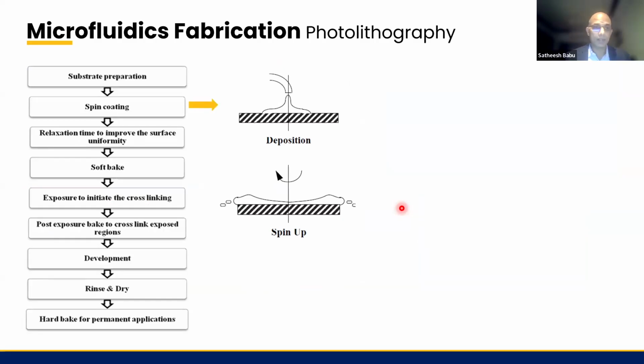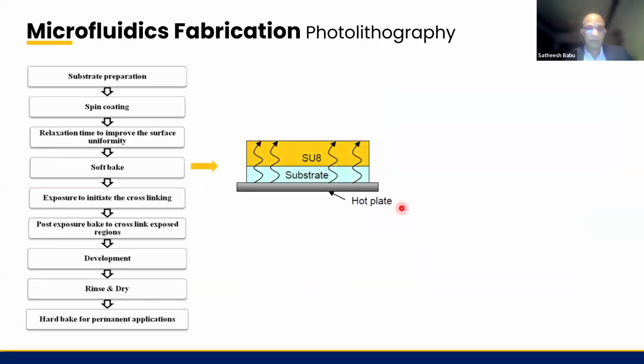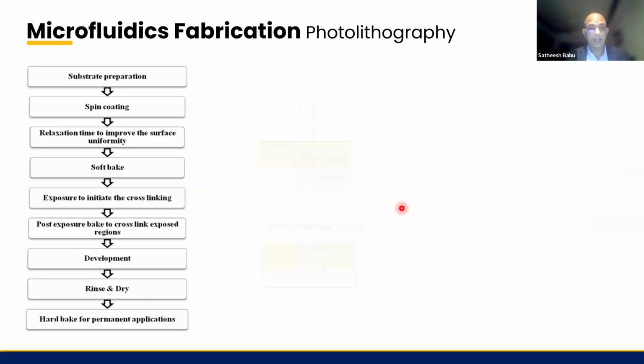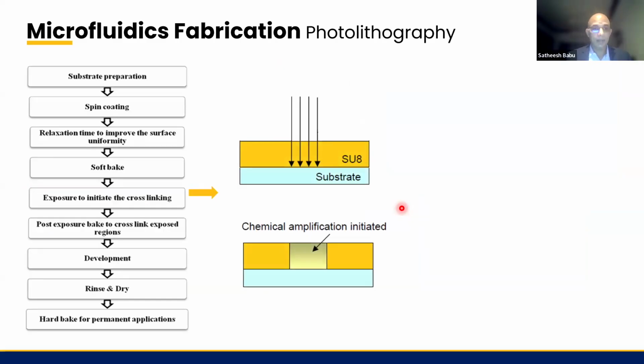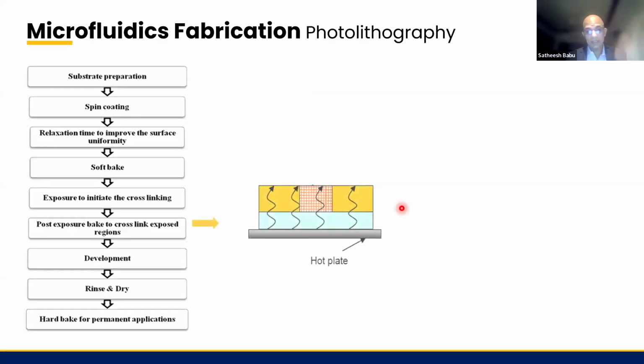At first, we prepared the substrate on which we spin coated the material. Then we did a soft bake, then exposure, and then a post-exposure bake, and we developed using a suitable solvent. So these were the multiple steps involved in the photolithography process.